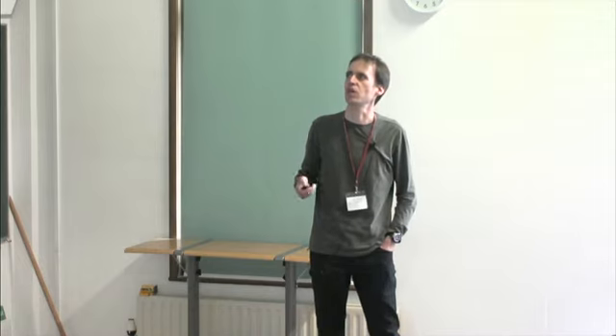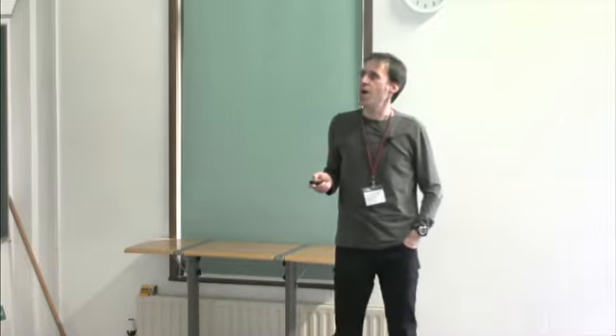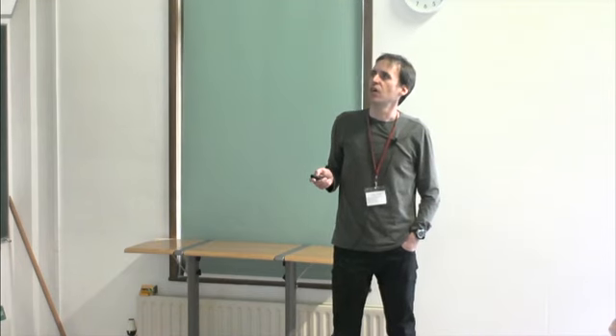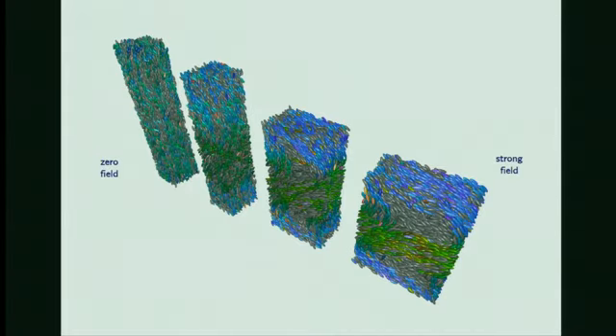So this actually may affect this distribution as well. But in a larger system, this distribution would probably be more similar to what you saw on this plot with the rotating ellipsoid and so on. Okay, now here you have a more artistic look of this event going from zero field to strong field. What you can also see here is that the lateral sample dimension somehow doesn't change very much, which was also observed